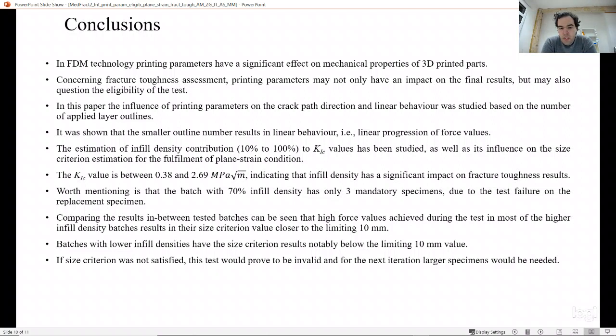Comparing the results in between tested batches, we can see that the high force values achieved during the test in most of the higher infill density batches result in the size criterion value closer to the limiting 10 mm. Just to point out that if the size criterion is not satisfied, this test would prove to be invalid, and for the next iteration, larger specimens would be needed.